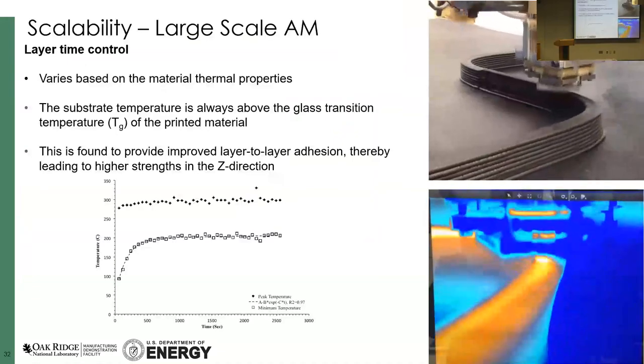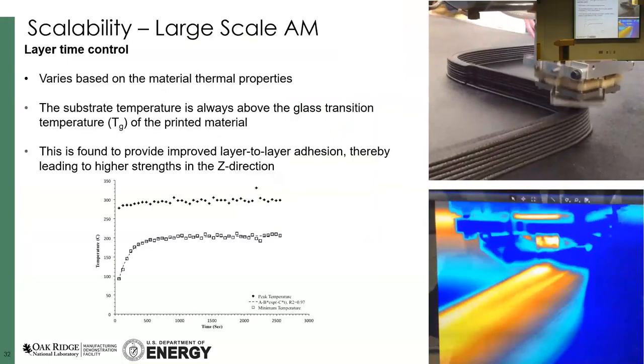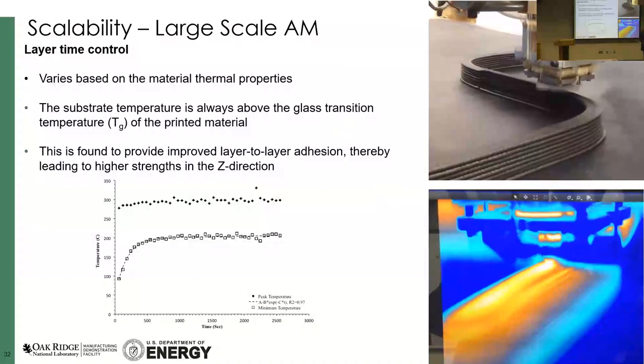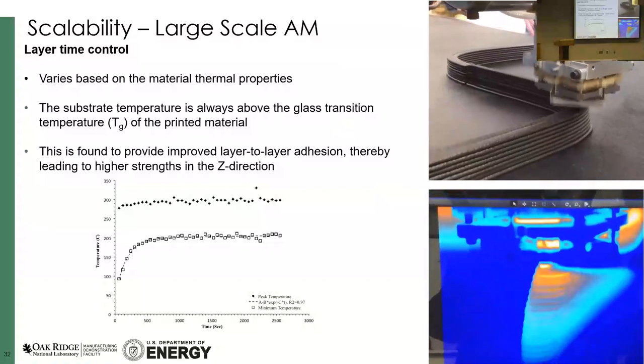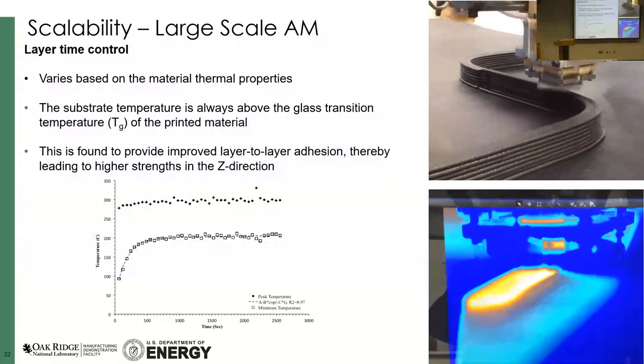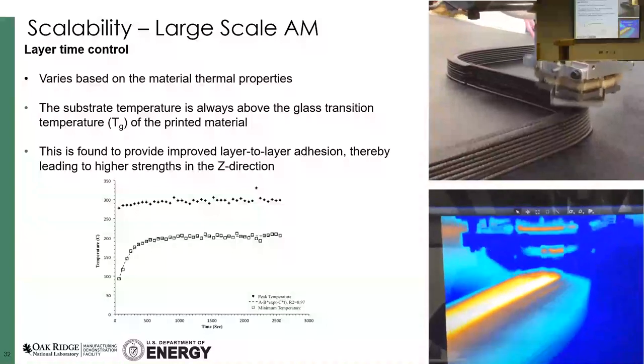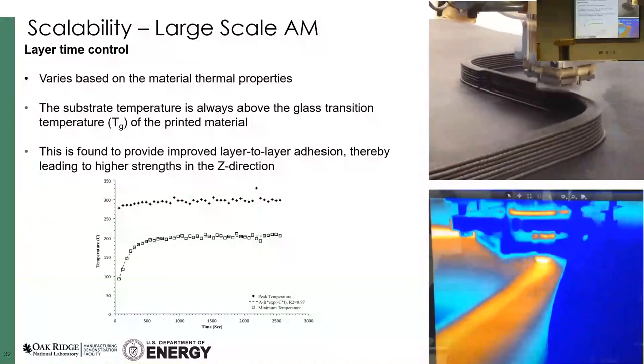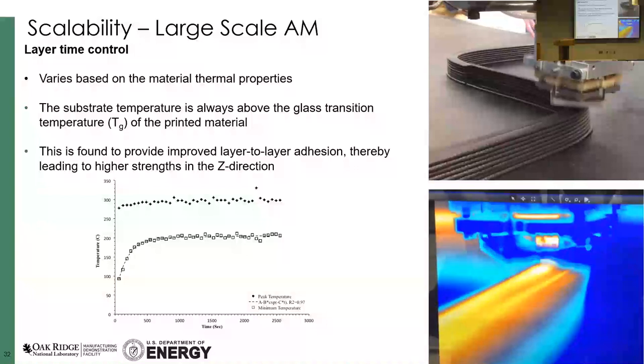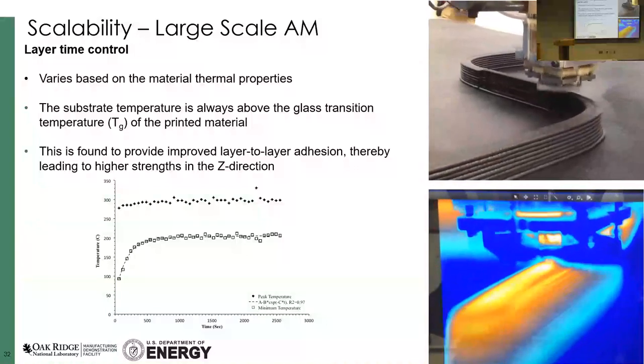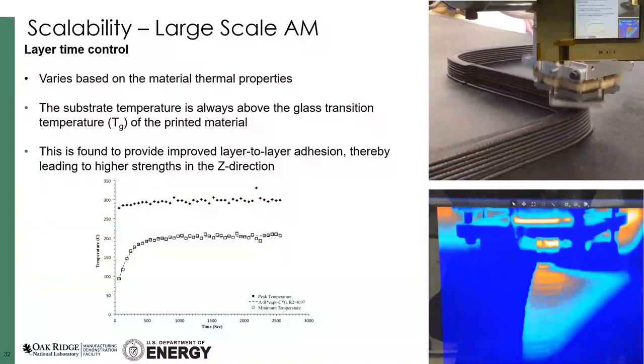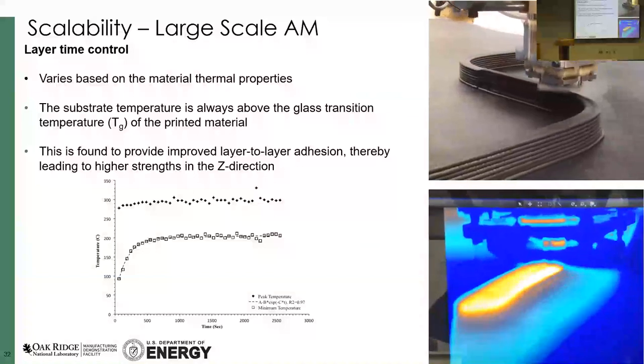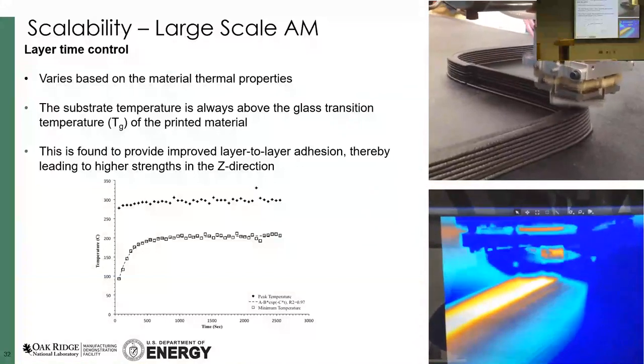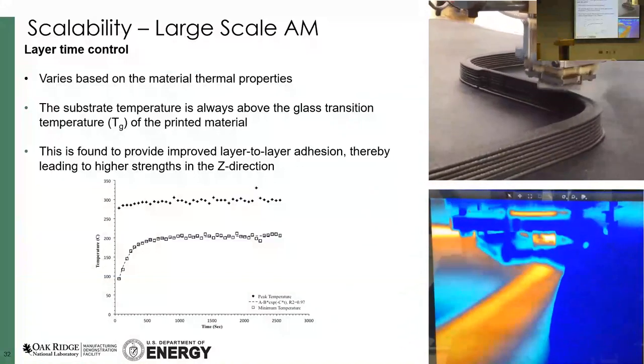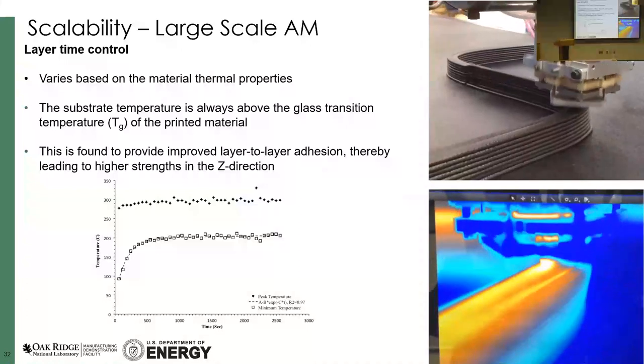Okay, after grieving, crying, going back to the whiteboard again, let's think about the process. Let's scale it up. We put an IR camera on there and found that even though we are printing fast, when we start printing an actual component with a very long layer time, the substrate drops down below the Tg of the material. You don't have enough heat of fusion between the layers. So you are printing something hot on something completely cold. What's going to happen? It will crack.